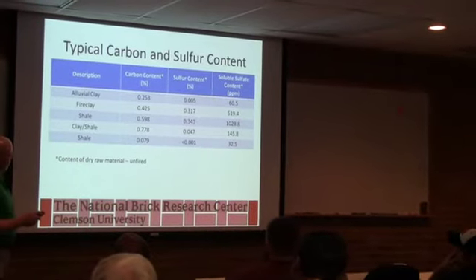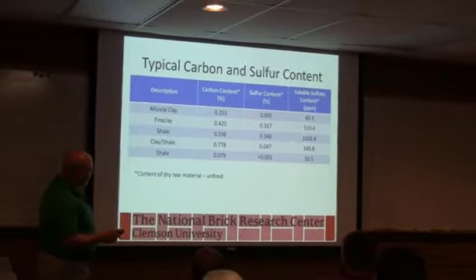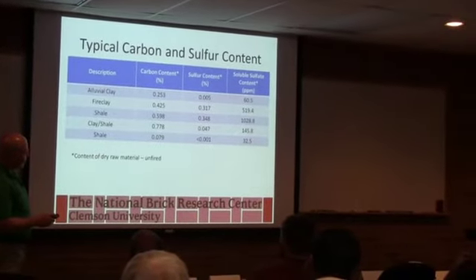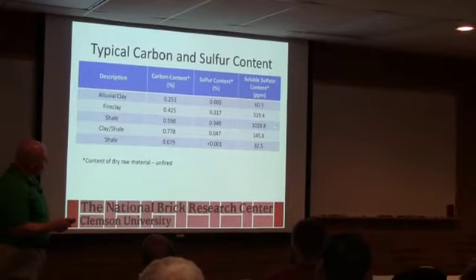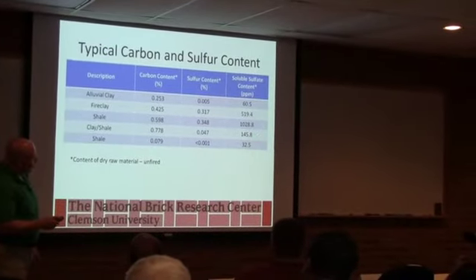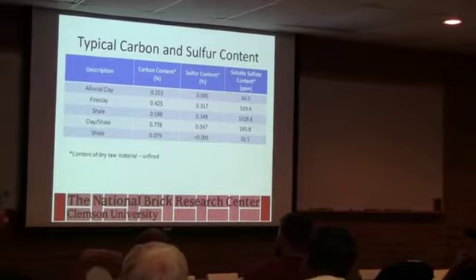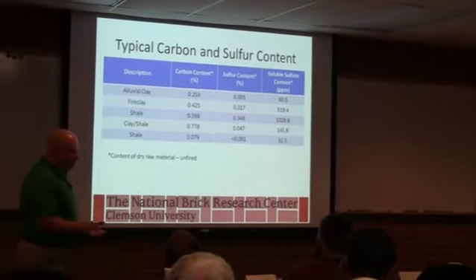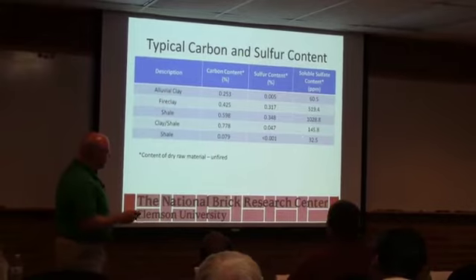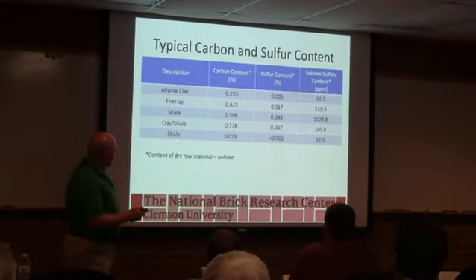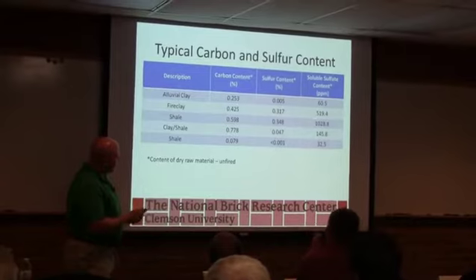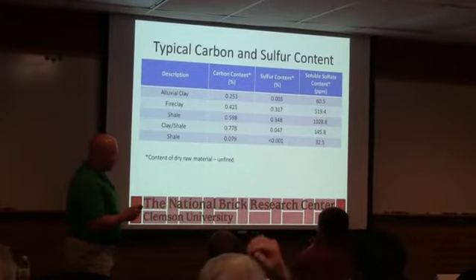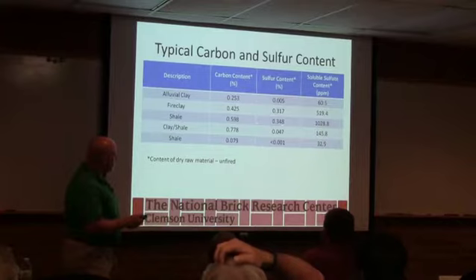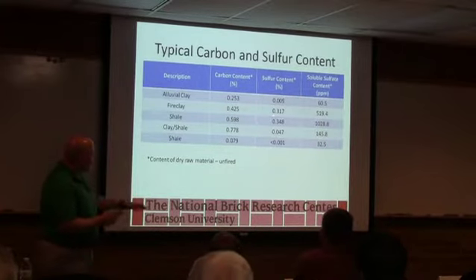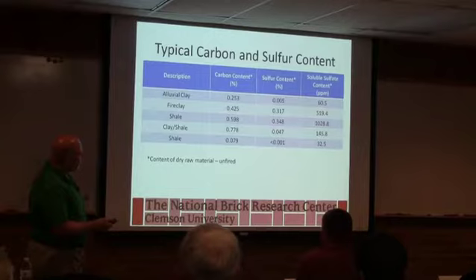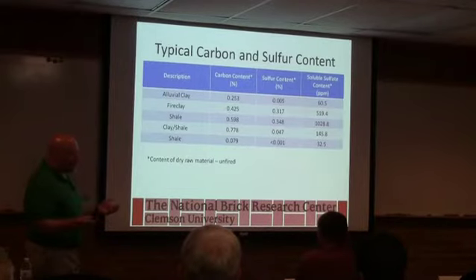But you know, when you start seeing numbers like this, as a general rule of thumb, working with soluble salts a lot, anytime this number gets to be over 100, there's a good chance you're going to have some efflorescence in the brick or scumming in the dry brick. So it's a fairly low threshold of what can cause it. You use these as process control or quality control if you can watch the raw material. So you watch the particle size, make sure it's staying relatively constant, and then you want to watch some, depending on what's going on.